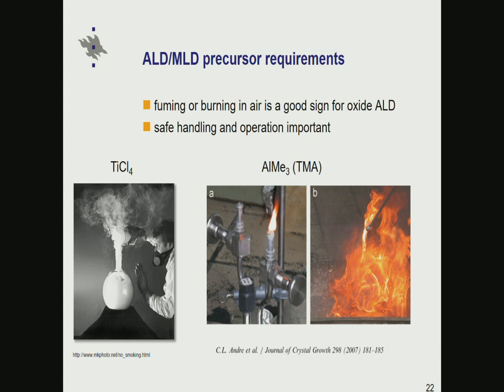And once you have done that, you should carry it out, and remember and notice that whenever you scratch this sand, it will start burning again. So you just need to burn it away, so that's the way how to handle it, but in a controlled manner. Titanium chloride is not burning, but it's producing this kind of a solid fume while reacting with moisture. So these are a little bit scary things, but the true fact is that these are good signs for a good precursor for oxide ALD at least.